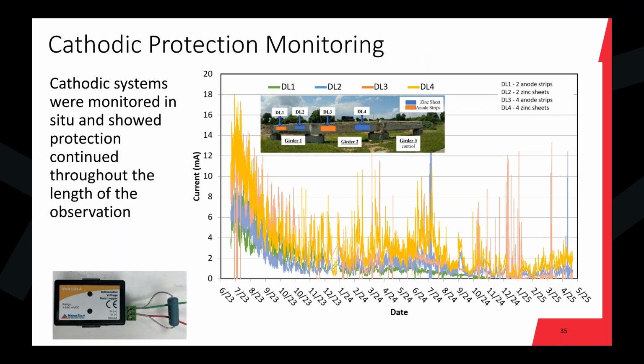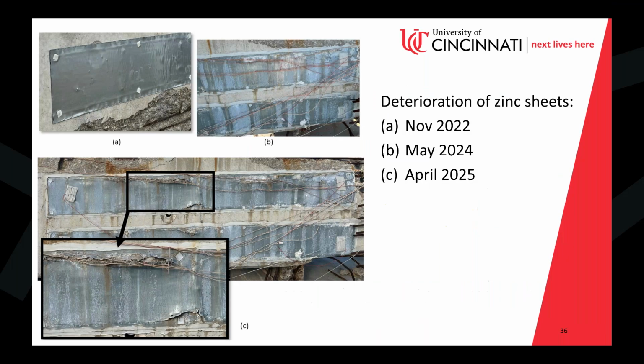And unfortunately, we stopped in May, but you're starting to see the uptick again. So what we're getting here is this fluctuating baseline of cathodic protection. And that really just means that everything's working as intended. Everything we measure here is corrosion that would have happened on the strands that we're protecting. You do see some pretty active deterioration of these zinc sheets. Again, it means it's working. This is corrosion that would have occurred to the steel inside the girder if it was not happening to the zinc. Top left, you see as installed, followed by after a good chunk of a year, and again.